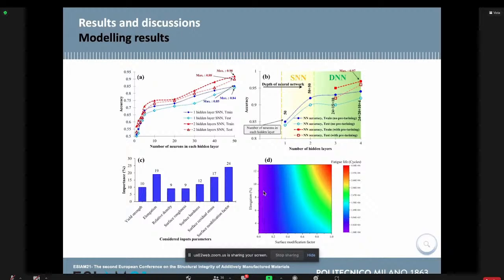Then we applied parametric analysis using the model function to estimate the fatigue life using these two terms, surface modification factor and elongation. It can be observed that by increasing surface modification factor and elongation, which can be increased by heat treatment, we can get higher fatigue life.